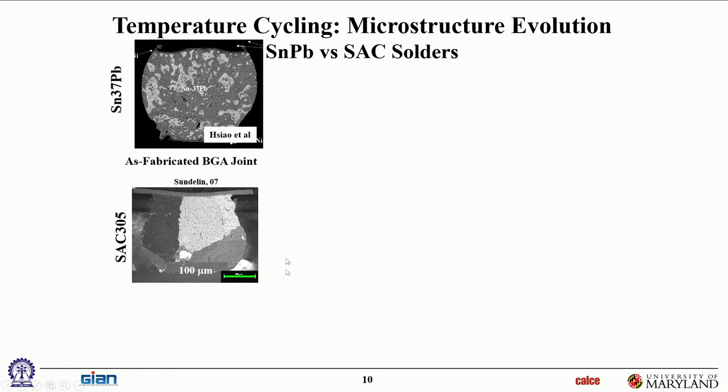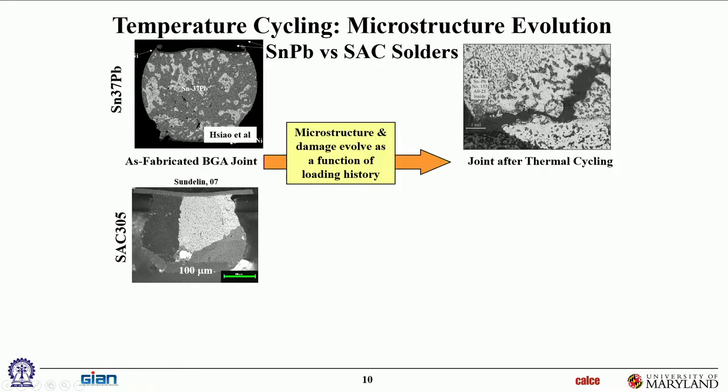He said, so this is like a composite material. It's like you've got six different materials because the tin has totally different properties in each of those six grains along the specimen direction. So when you have a composite material like that, what do you call a stress strain curve? Because each grain is contributing a different stress strain curve to the overall structure. So life gets complicated. We usually take some kind of an average, a volume averaged value. The next question is, the microstructure is not going to stay like this. As you temperature cycle, it's going to evolve. This is actually after it's failed, but if you look at the portion that has not failed, you can see that it's coarsened a lot.